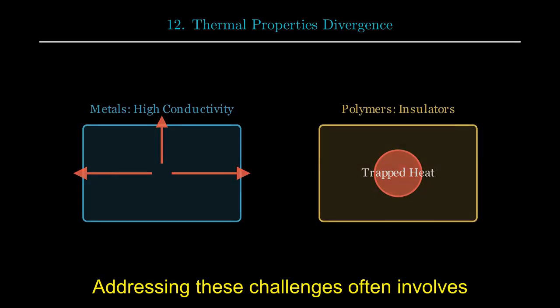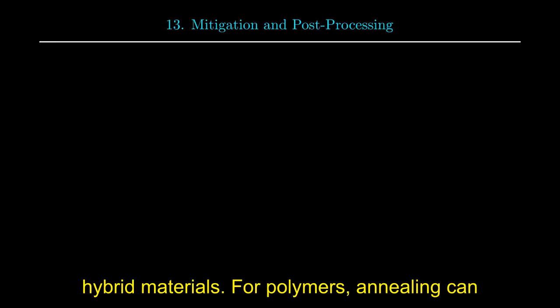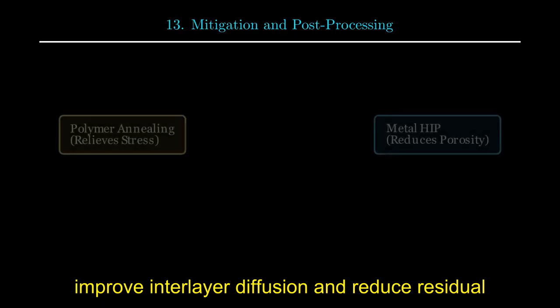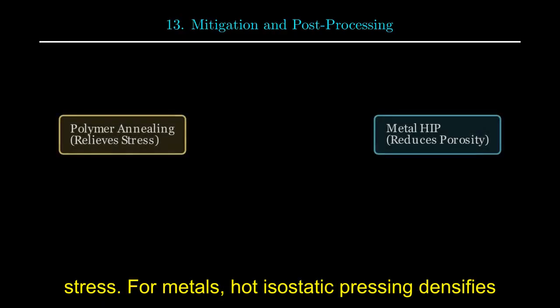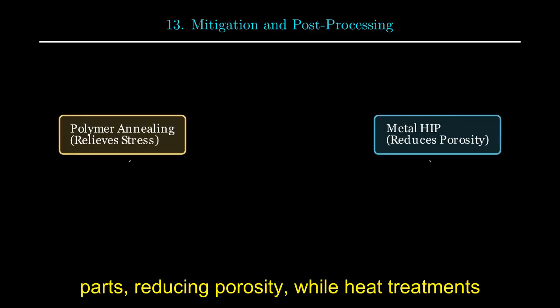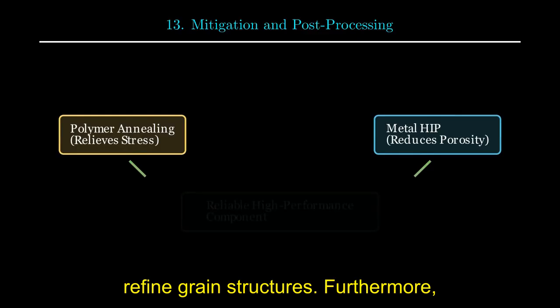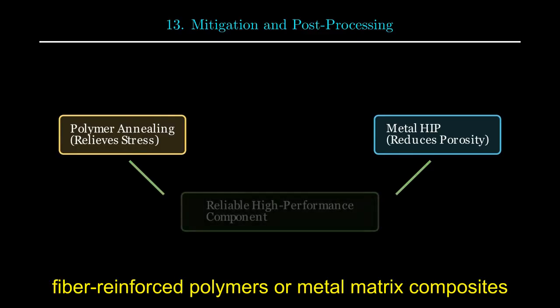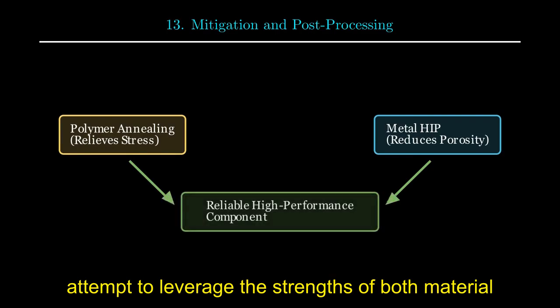Addressing these challenges often involves sophisticated post-processing or the development of hybrid materials. For polymers, annealing can improve interlayer diffusion and reduce residual stress. For metals, hot isostatic pressing densifies parts, reducing porosity, while heat treatments refine grain structures. Furthermore, fiber-reinforced polymers or metal matrix composites attempt to leverage the strengths of both material types.